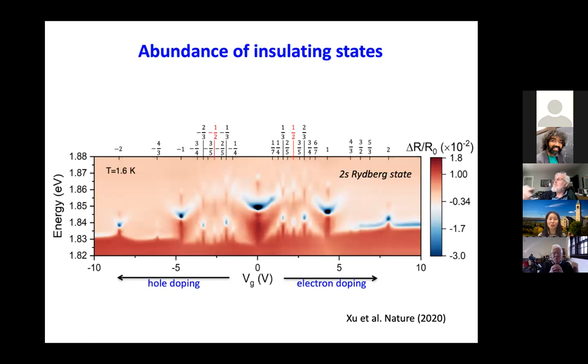So remember, the sensor is neutral. It doesn't have any doping. We have a sample layer there, and we keep putting in, on average, let's say here, 1 electron per site, 2 electrons per site, and on the other side we'll have 1 hole, 2 holes. The color tells us about the absorption strength, the spectral weight. When the sample is charge neutral, my sensor sees the largest exciton binding energy and also the largest spectral weight, the largest absorption. Now if I come in with 1 electron per Moiré site in my sample, my sensor sees smaller binding energy and also a little bit smaller absorption.